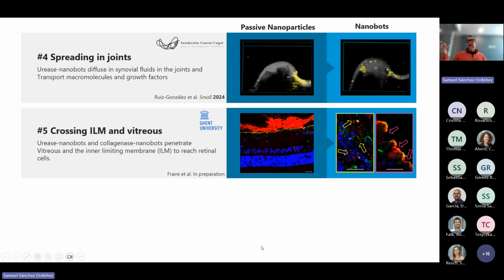What else? Another place where there's a viscous layer is the eye, right? Crossing the ILM, the inner limiting membrane, is very, very challenging. So passive nanoparticles, here in red, will stay on the outer side. They never reach the cells. But nanobots are able, in this case with collagenase and urease, to degrade sequentially and very mildly the collagen, and then make these gaps that allow them to reach the cells.